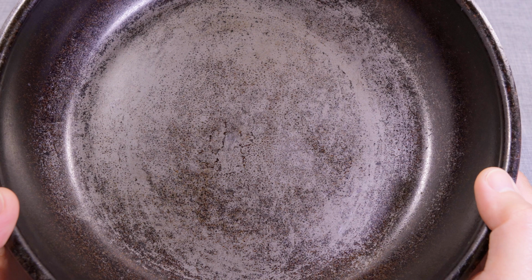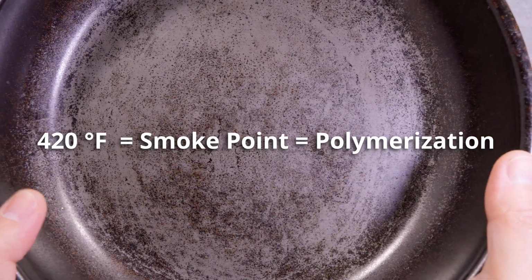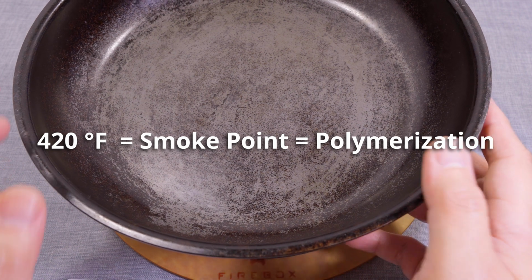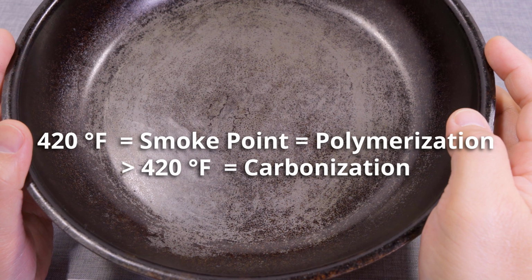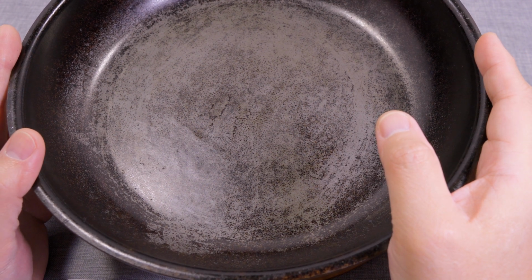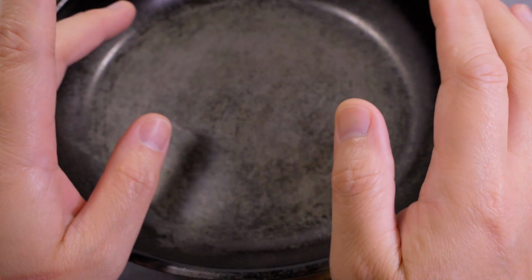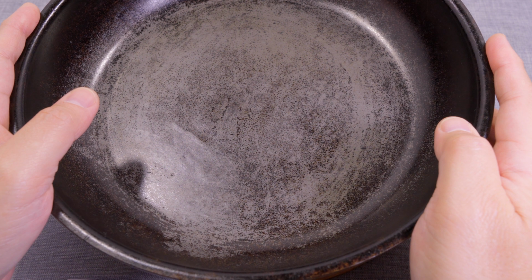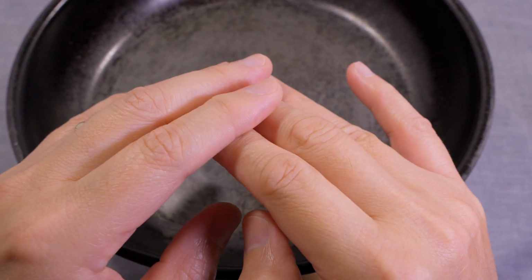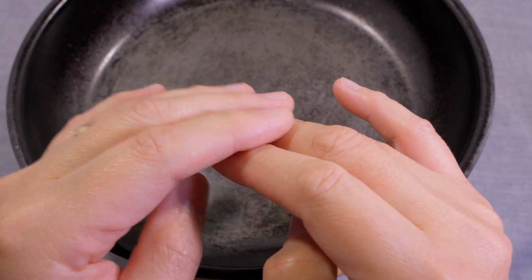Why only 30 minutes? So I'm going to get nerdy here for a second. Here's what we know. The smoke point of grapeseed oil is 420 degrees. We know through science, I have a link in the description for that too, that polymerization occurs at the smoke point of the oil, and carbonization occurs at temps above the smoke point. My theory for this old method is, the first few layers is getting the oil to a point of polymerization, and that last step of the 500 degrees for 1 hour will take all the layers to full polymerization, all the way through, to a point that it might even be starting to carbonize. So what you should end up having is one nice thick, well-fused layer of seasoning instead of 6 individual carbonized layers, I guess.